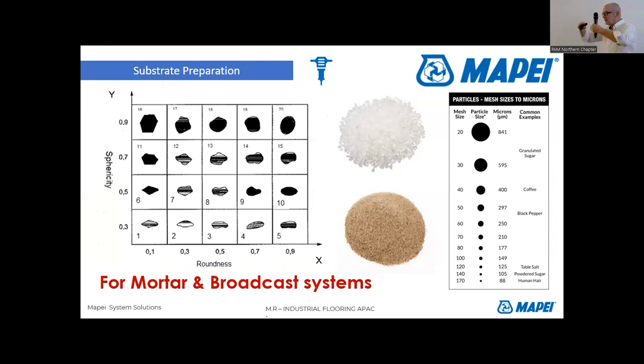Once you give weight onto it with a power floating machine, you get this density. This usually is done by selecting four to five different sand sizes. You see on the sample, the very rough one is the sand selected by the applicator, and the very dense one is our product. You see how much material we need to put on top of it, the closing of the pores, the filling of the walls, the grouting. It takes more material, it needs more money.